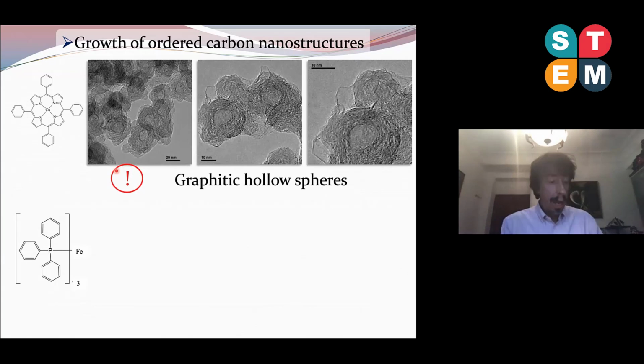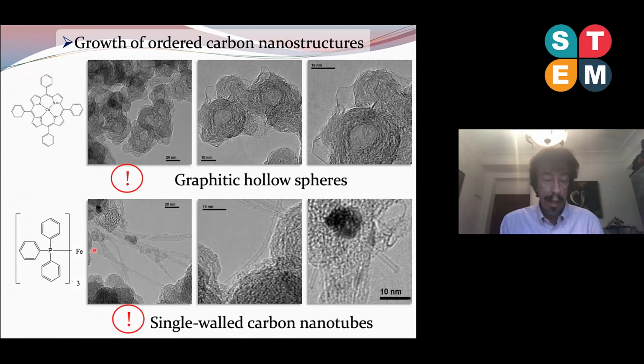We also got some other interesting and exciting results by using this kind of tetraphenyl porphyrin, and by using this triphenylphosphine derivative. And we got different results in these cases. In one case, we got the formation of graphitic hollow spheres, a different material which was not so evident in the other materials. And very interestingly, by irradiating this precursor, we obtained single-wall carbon nanotubes. As you can imagine, we did pioneering work on carbon nanotube production. So we are really excited that we get more ordered carbon nanostructure growth also by doing this kind of experiments.